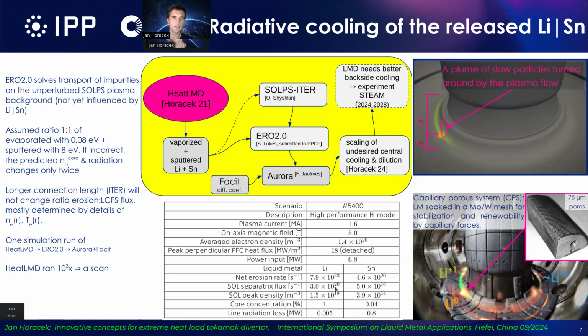And this is the separatrix flux. And you see that it's 3 orders of magnitude lower, or even 4 orders of magnitude lower for the case of tin. And then, unfortunately, even this is too strong. So even if you decrease the amount of tin particles by a factor of 10,000, you get nearly 1 megawatt of radiative power with only 2.5 megawatt going to the divertor. So like one third of what is going into the plasma. So it means that you are getting very close to the disruption limit, radiative collapse, in fact, for the case of tin. For the case of lithium, it's not the case.